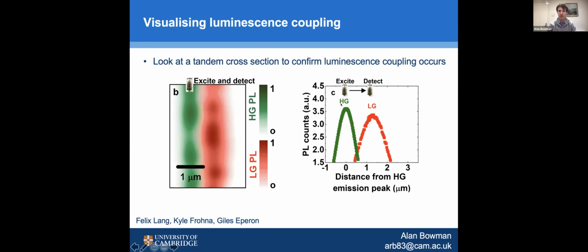We were able to shine laser light on the green layer, the high band gap layer, and then observe emission from the low band gap layer. And we were able to show that there's light going in, being transferred across, and then coming out, which is this process of luminescence coupling that we found was surprisingly important in these materials.